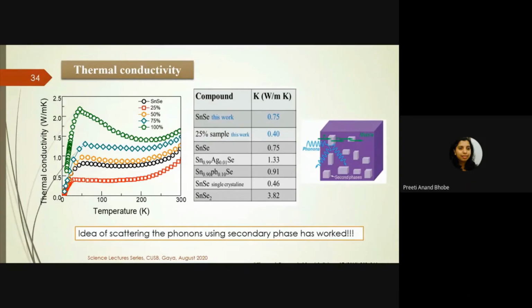So all the three strategies that I talked about for improving ZT, which was the objective, are achieved. You dope copper, you get modulation in the microstructure. You dope other elements, you get energy levels being formed near the Fermi level, which is trapping the carriers and hence reducing the electrical conductivity, but it is improving the thermal conductivity. In the composites also, we see that we can improve the thermal conductivity.